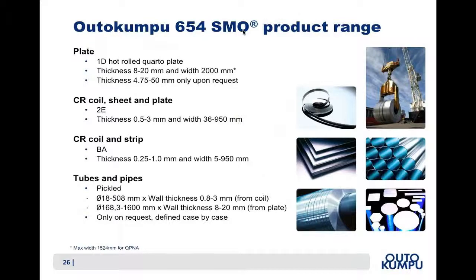In terms of the product forms, the range for 654 SMO will be more narrowly focused than customers might expect with the more mainstream grades. We've got material available in plate, hot rolled quarto plate, which will be from 8 to 20 millimeters thick, but also from 4.75 to 50 millimeters on request. We can provide cold rolled coil, sheets and plates from 0.5 to 3 millimeters thick, and then we have cold rolled coil and strip in bright annealed, BA, which is 0.25 to 1 millimeters thick. Complementing this range of flat product, there are also some tubes and pipes available in some commonly required dimensions.